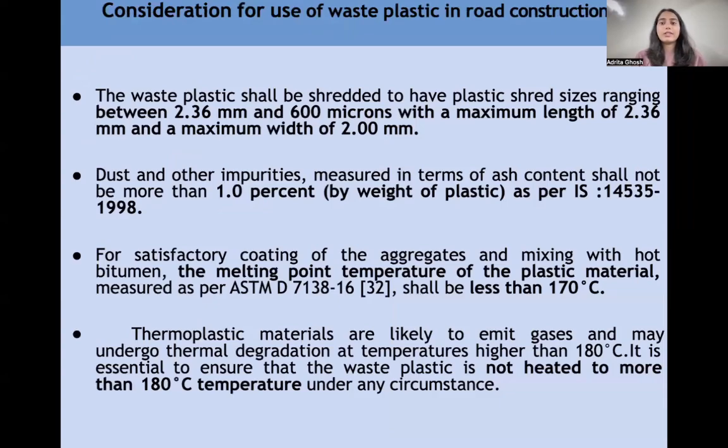Consideration for use of waste plastic in road constructions. The waste plastic shall be shredded to have a size ranging between 2.36 millimeter and 600 microns, with a maximum length of 2.36 millimeter and a maximum width of 2 millimeter. Dust and other impurities, measured in terms of ash content, shall not be more than 1% as per IS 14535